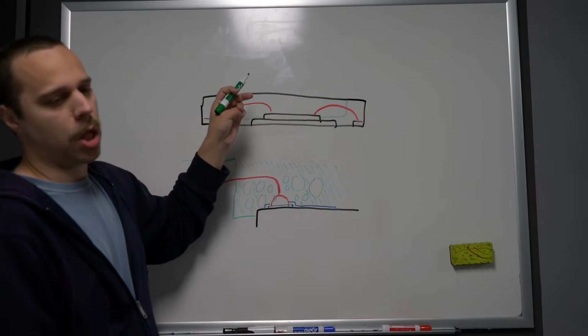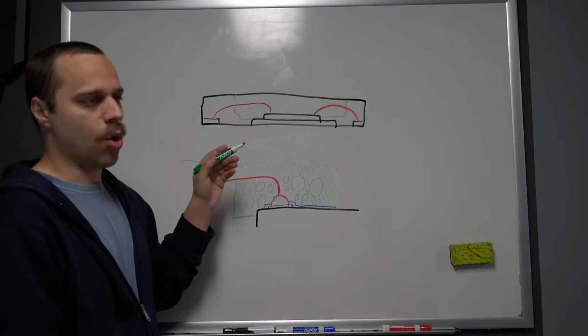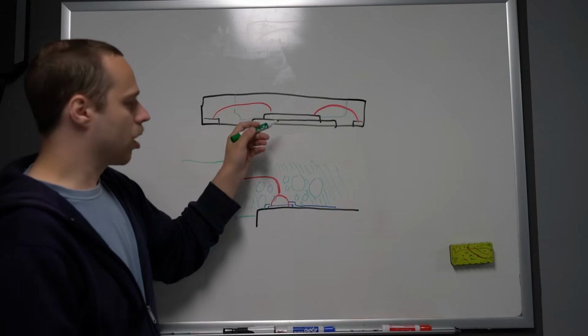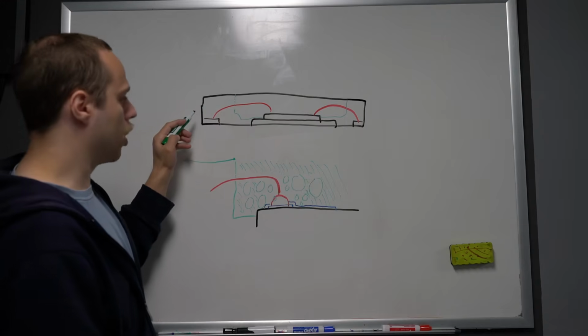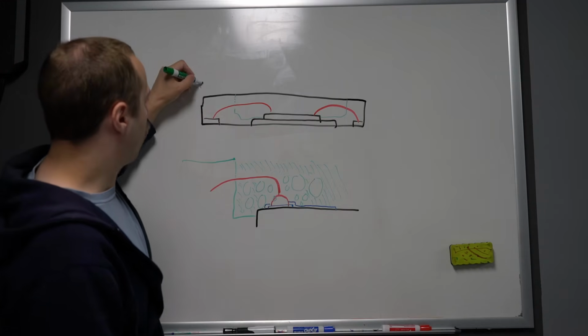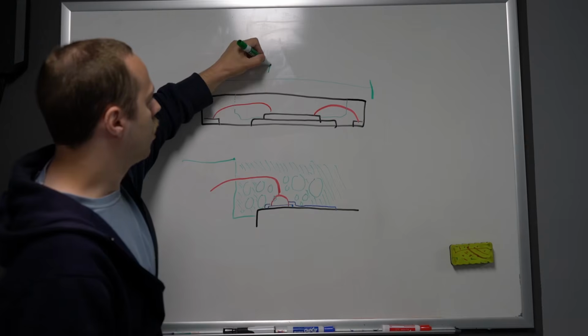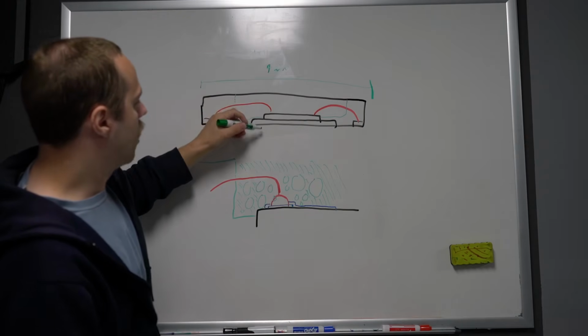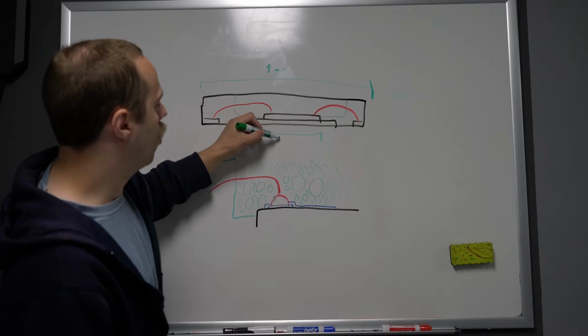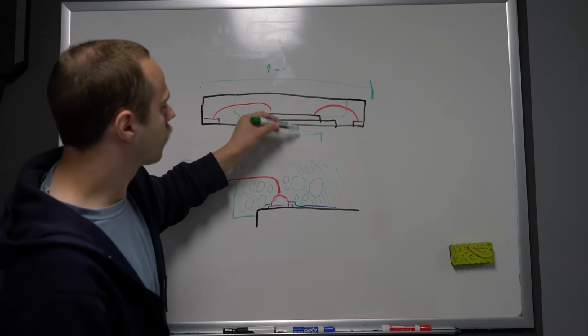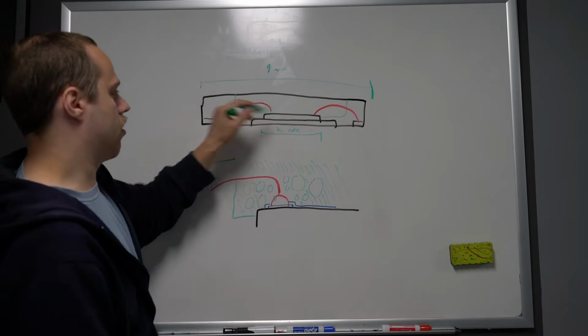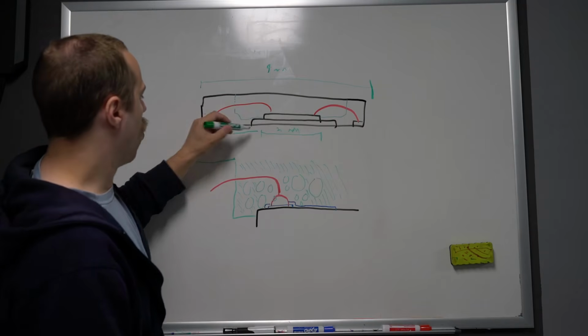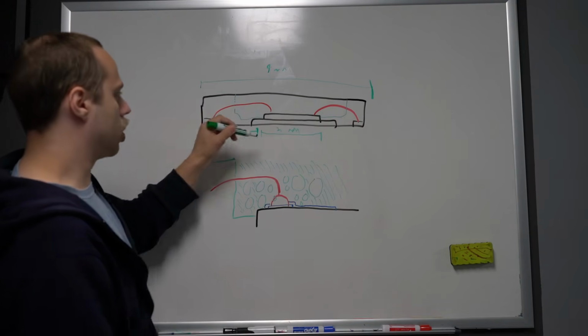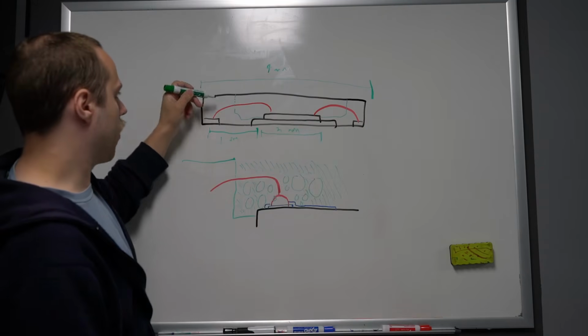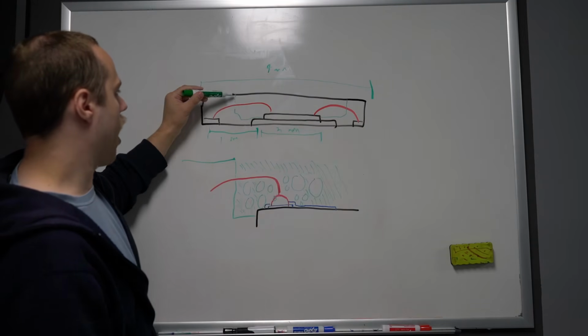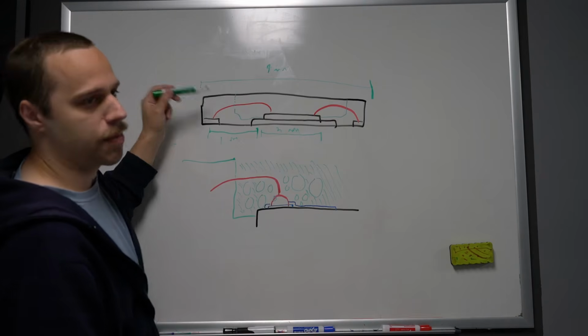And on a smaller package, often you need to use some sort of masking technique in order to keep the acid exactly where you want, and that's what we're going to be doing on this device because, again, it is a fairly small QFN. We're looking at 4 millimeters across the entire device, and the die size is about 2 millimeters. This is obviously not to scale, but I've only got about 1 millimeter of margin on either side, so we are going to need to use some masking to make sure that we have a lot of removal here and essentially no removal here, and we've only got a millimeter to work with.